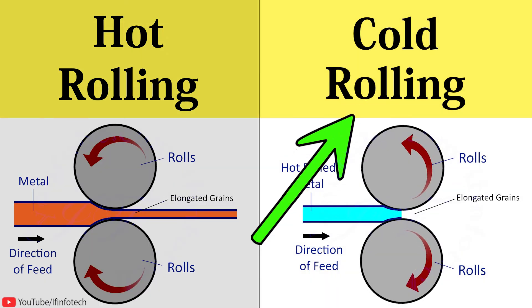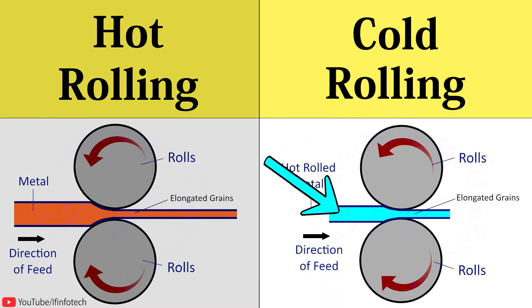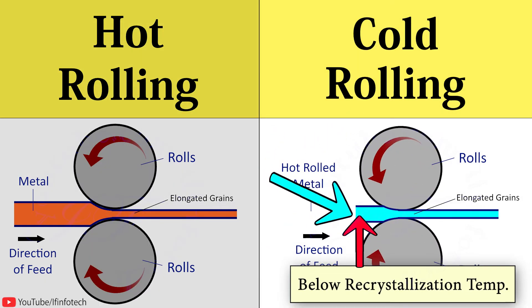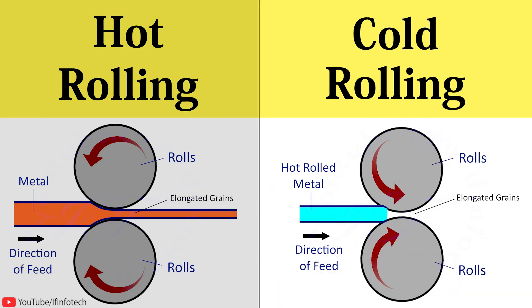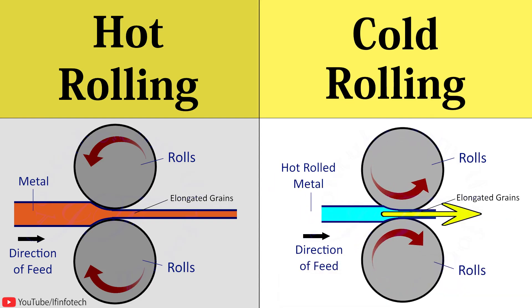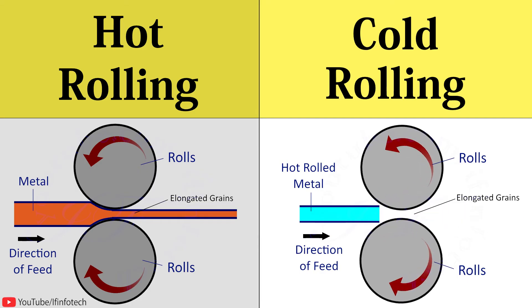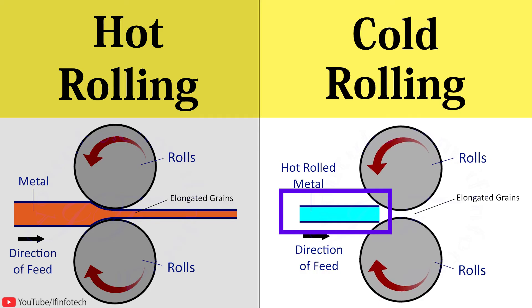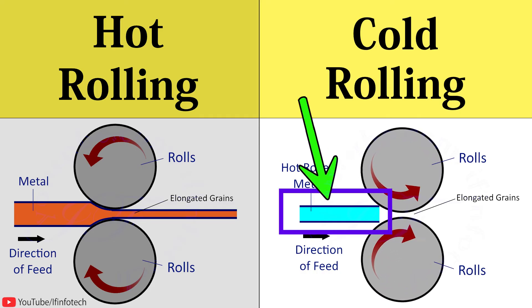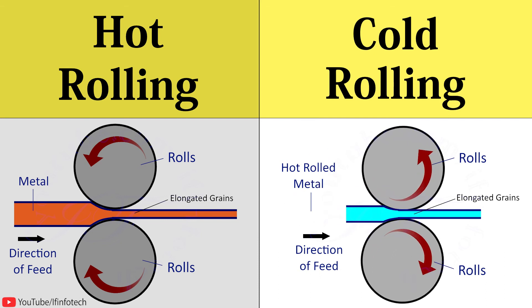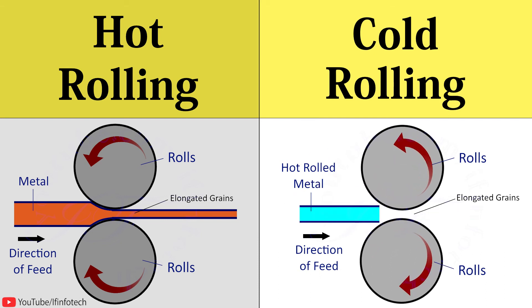In cold rolling process, the metal is fed into rolls when its temperature is below recrystallization temperature. Cold rolling process is employed for providing smooth and bright surface finish to previously hot rolled metal. Before cold rolling process, the hot rolled products are cleaned through pickling and other operations. The part being rolled is generally annealed and pickled before the final pass is made, so as to bring it to accurate size and obtain a perfectly clean surface.